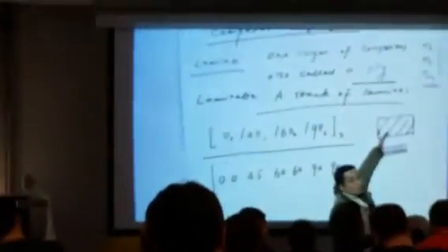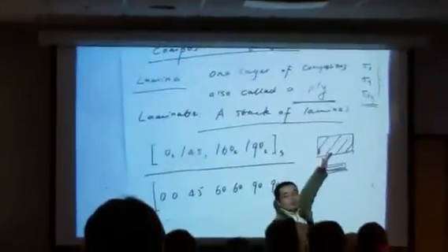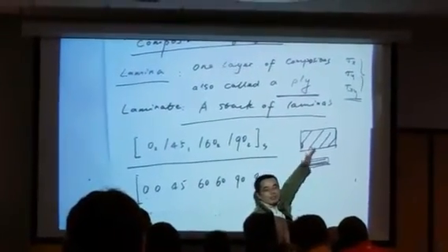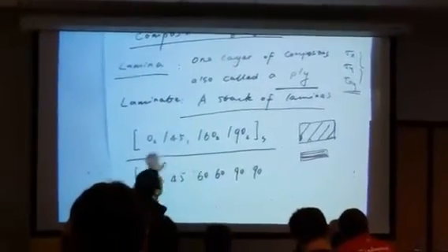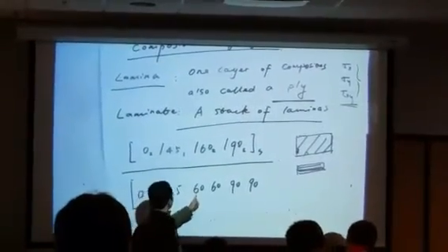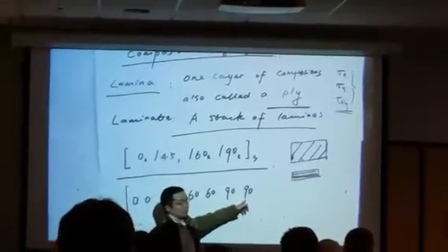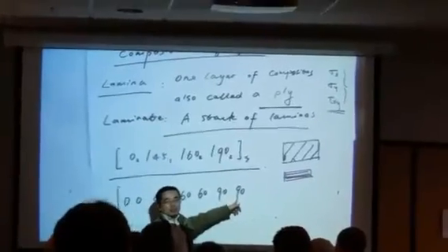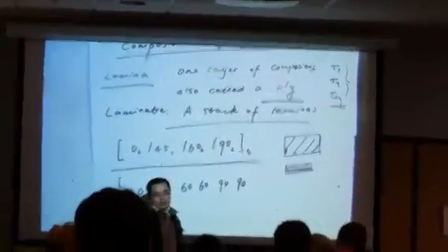And then above this, you want to have a 45, 1. That means you want to have 1 layer of composites, 1 ply. In that ply, the filament is along the 45 degree direction. Okay? Basically, this is the meaning. And how many layers in total? 1, 2, 3, 4, 5, 6, 7. And we have symmetry. So in total, we have 14 layers, 14 plies.